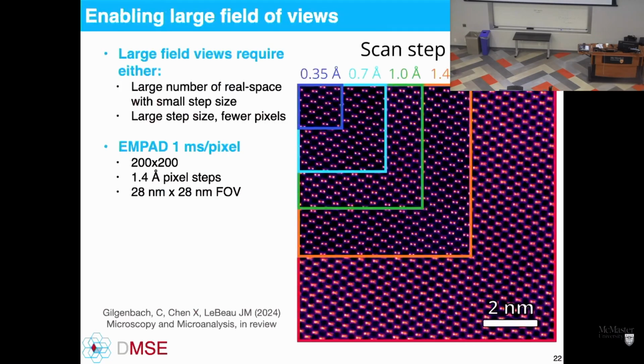And more importantly, if you need a large field of view, you can change the way you acquire your data so that you can get 1.4 angstrom spacing between the positions in real space, to give you resolution that's still on the order of about 20 to 30 picometers from 1.4 angstrom probes. So what this means is you can use a fairly small number of pixels in real space and get a much more finely sampled and much higher resolution than you would conventionally. So much lower dose on the material, etc. And this gives a 30 by 30 nanometer field of view that is readily possible.